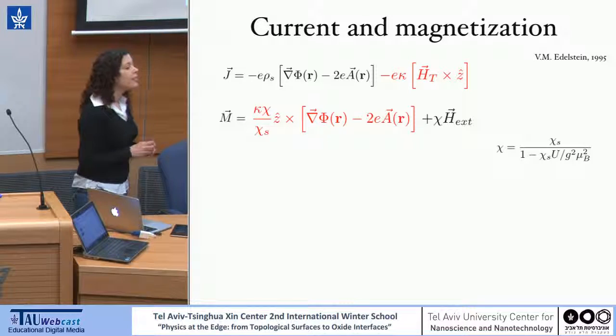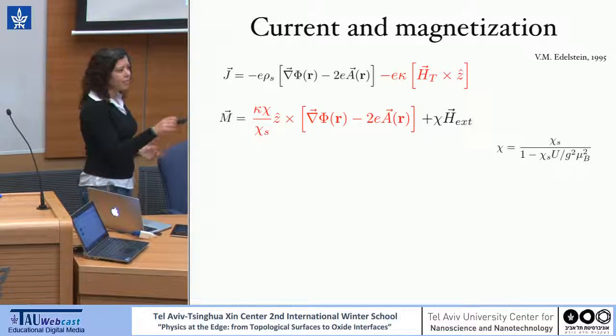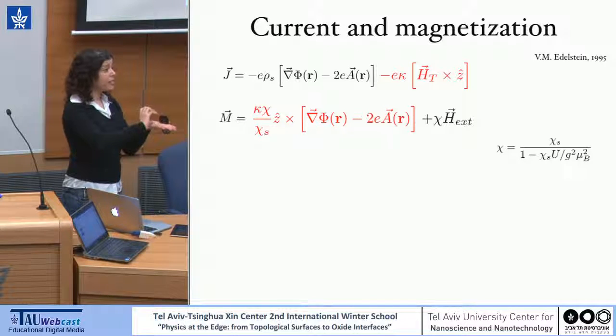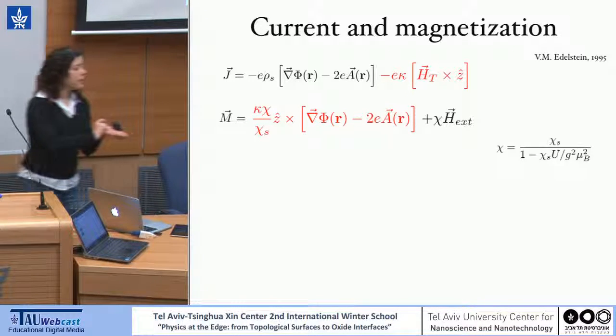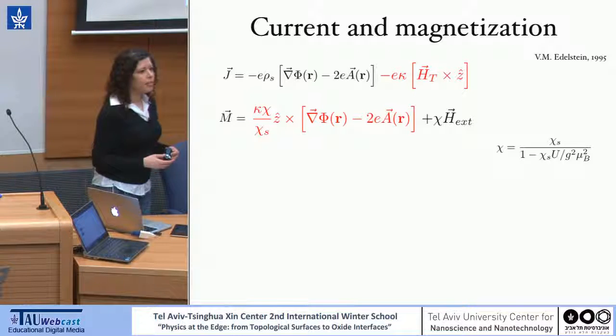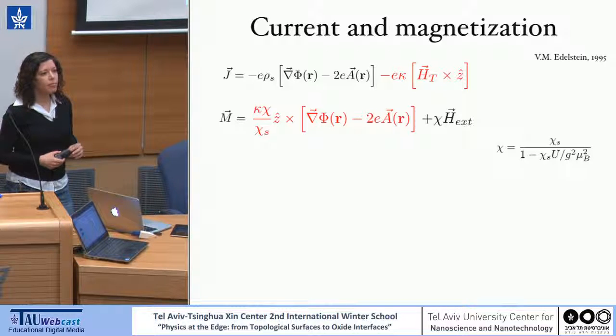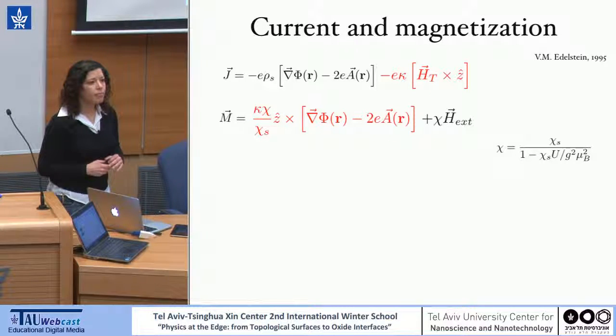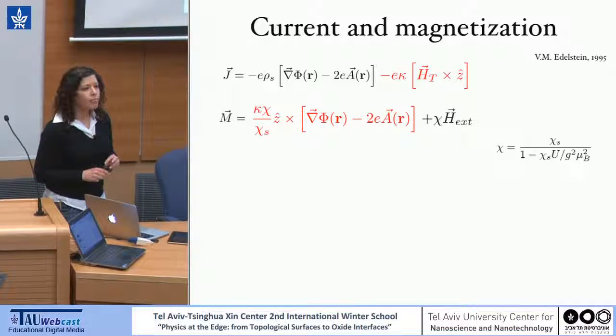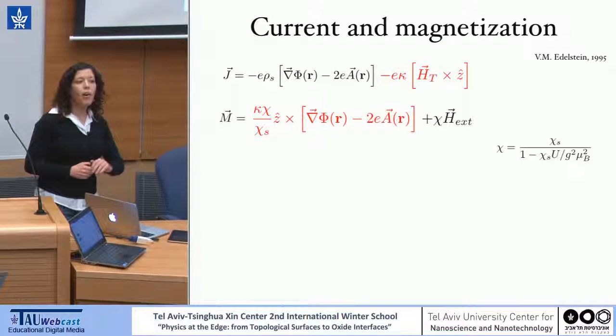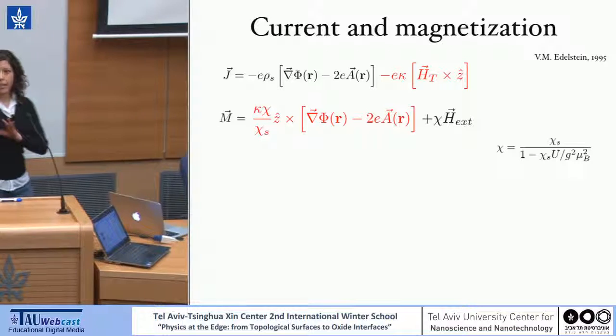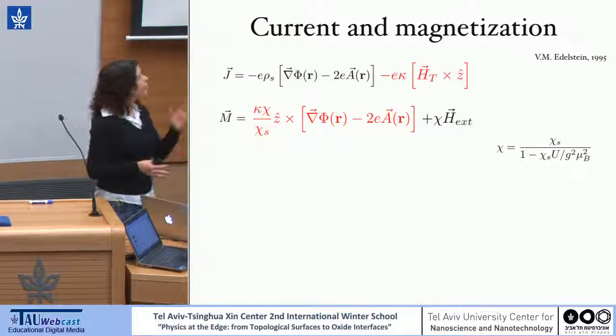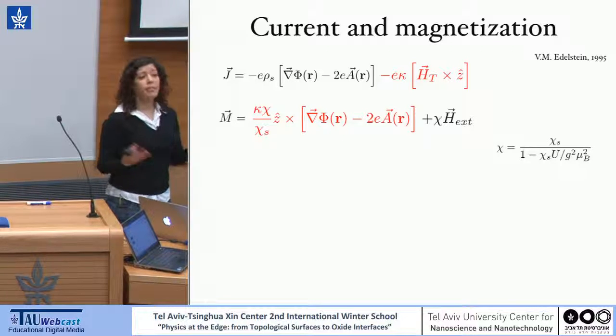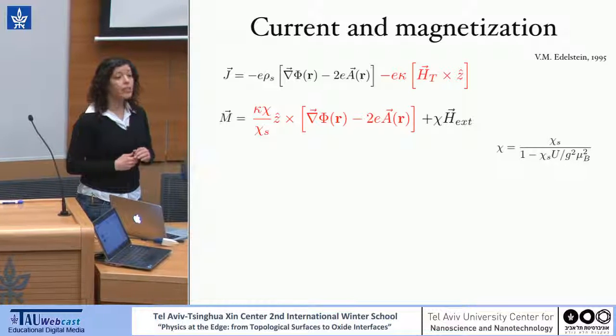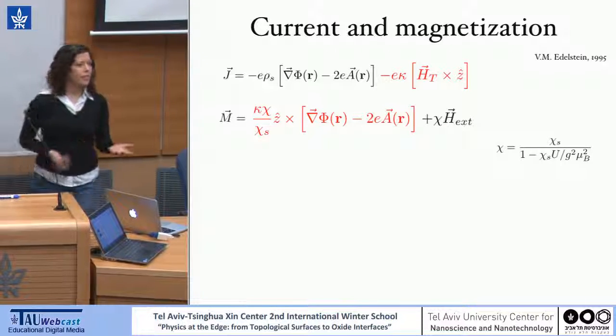For lead, spin-orbit mechanism is Rashba? For lead, okay, it depends, because when they are looking at thin films of lead, I would assume that that will be the most important mechanism. In the bulk, obviously not. Since you mentioned this Gor'kov-Rashba paper, they predicted, as far as I remember, that you have also a P-wave triplet component. Do you have it also in your model? No. So I was assuming that I'm only looking at the S-wave component, again, as I was mentioning before, coming from the fact that I assume that I have enough disorder that will kill the P-wave component. So the disorder just washes out the P-wave? Yes. And that doesn't change if you have spin-orbit coupling.